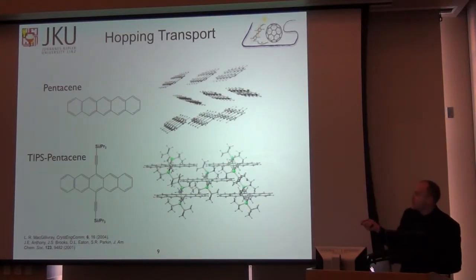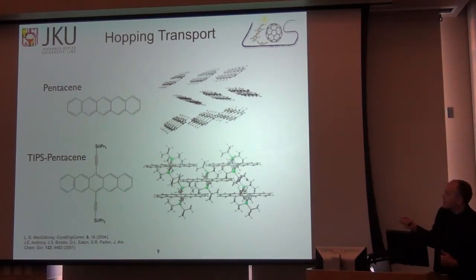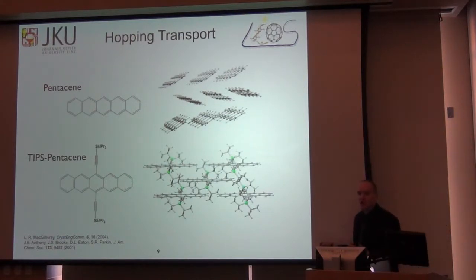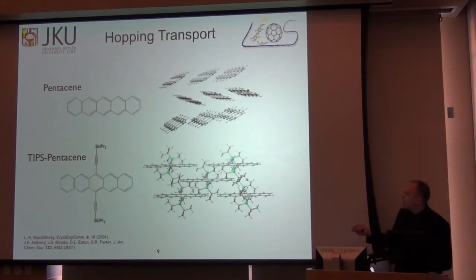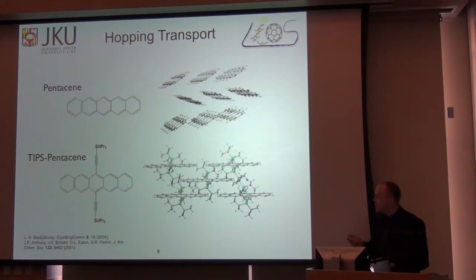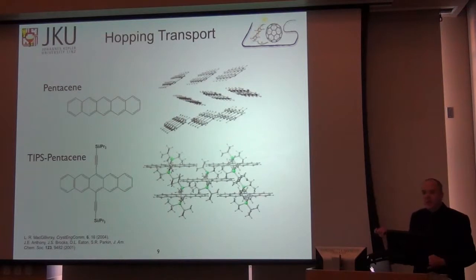This is an example of pentacene up here, which is probably the most well-studied organic semiconductor in the history of organic semiconductors. And when pentacene packs into a crystal, it forms van der Waals crystals, and it forms this kind of loosely packed and not very cofacial herringbone structure here. And so this TIPS pentacene is one example of molecular engineering where you add on these bulky side groups, which intuitively would say we're taking up volume with useless junk. How can this make the device better? But because the crystal packing is so much closer and more cofacial, you can actually improve the mobility and conductivity in the pentacene. And so that's just a brief introduction to organic semiconductors.